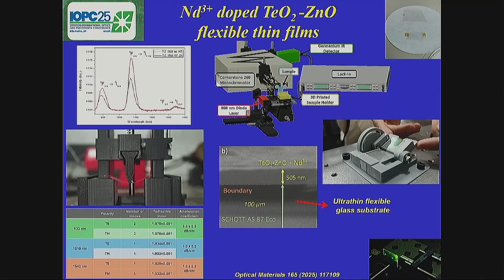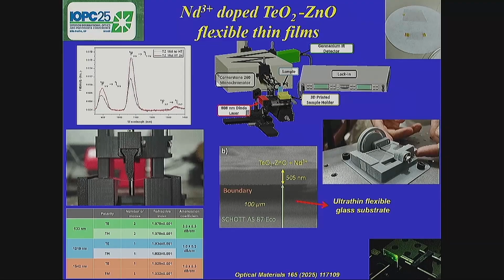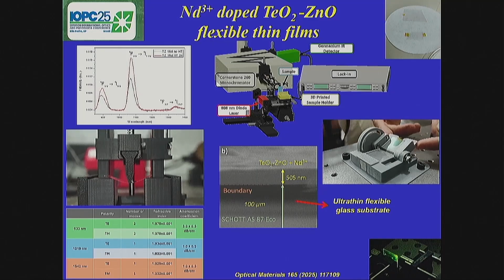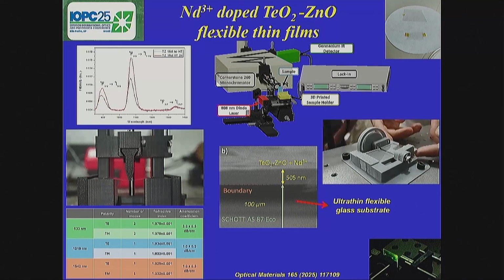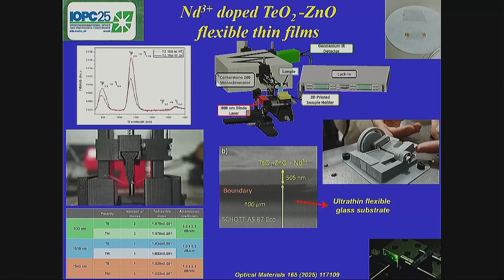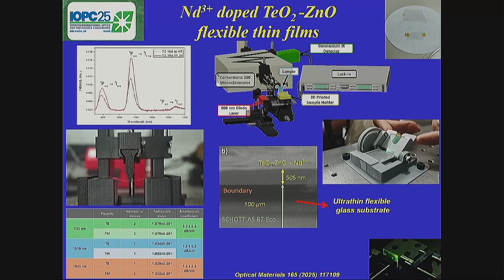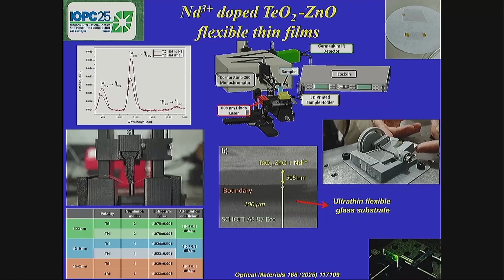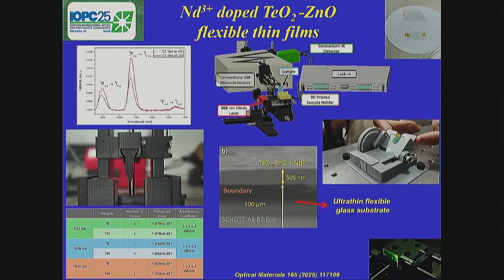In this image obtained by scanning electron microscopy, it's possible to see the thickness of the thin film of about 500 nanometers. It was deposited on a ultrathin flexible glass substrate with 0.1 millimeter thickness. The 3 important emissions of neodymium could be measured by this experimental setup. And here I think it's not moving. It's not working. Yes, it is. It's possible to see that the flexibility of the substrate was not compromised by the presence of the tellurite thin films.